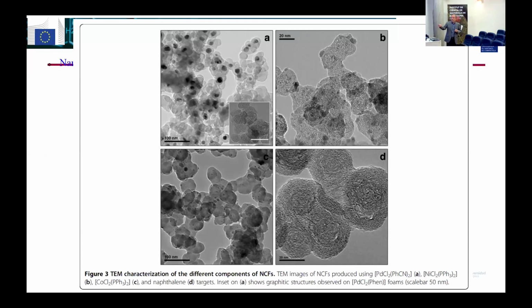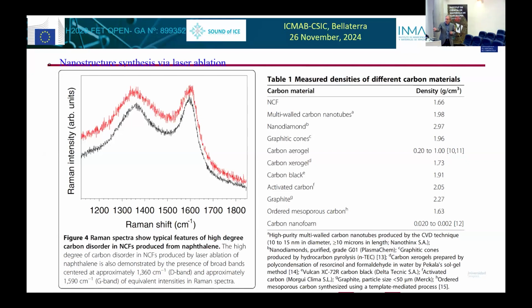And this is the typical structure that you see with this product. You have metal particles inside this matrix, and you have to look carefully to see the graphenic structures all around. I don't think I can see them very easily here. If anyone is interested, if you look carefully at a high resolution picture of this, you can see that you have graphene planes embedded in this sort of amorphous structure.